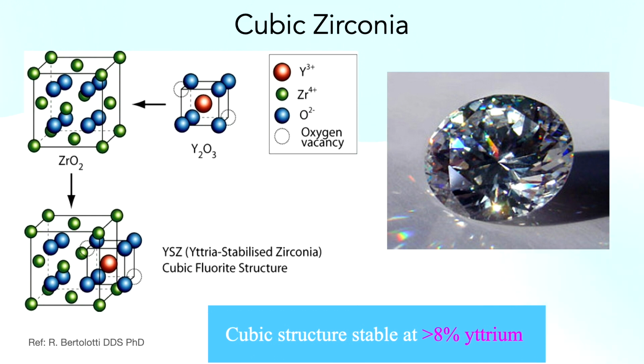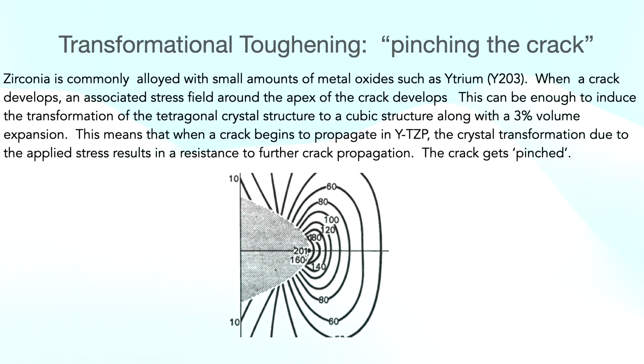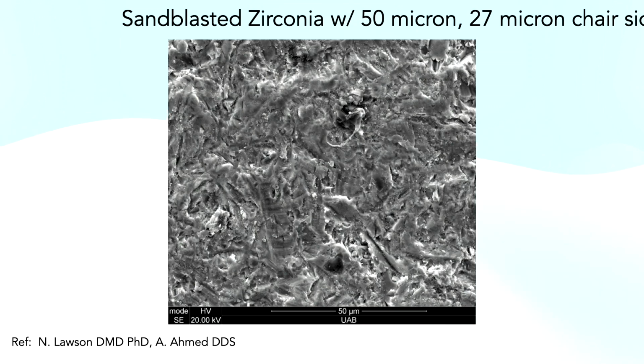If you dope it with enough yttrium, you can get cubic zirconia. But what's really interesting about zirconia, the Y-TZP zirconia, is that when a crack starts to grow in it, you get an increased concentration of force here, but that results in an expansion, about 3% of the zirconia. So that expansion changes the crystal structure of the zirconia and essentially pinches that crack shut. That's why zirconia is so crack resistant, fracture resistant. Okay? Yeah, and that's what sandblasted zirconia looks like.